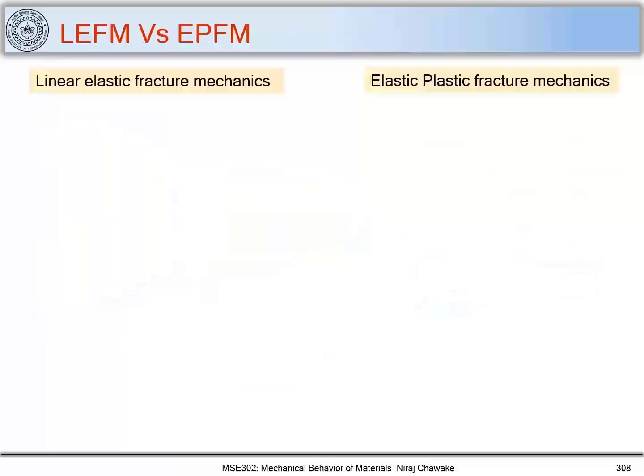Now let me move on and introduce two fracture mechanics approaches we use to understand fracture in materials. One is linear elastic fracture mechanics, another is elastic plastic fracture mechanics. So linear elastic fracture mechanics works very well with brittle materials we have already looked at, and with a material which has a very high strength, like more than 1400 MPa. For such kinds of materials you can comfortably use linear elastic fracture mechanics. However, when the material deforms plastically or materials are ductile, you should use elastic plastic fracture mechanics to understand the fracture behavior of such materials.